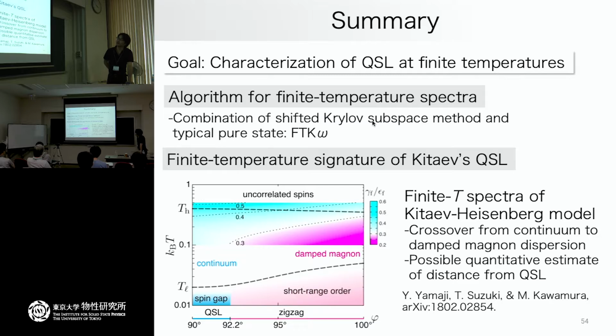And we found that the finite temperature signature of the Kitaev spin liquid phase really appears in the peak width of the spin excitation spectrum. This ratio gives us a crossover behavior from the continuum excitation spectra to the damped magnon spectrum. And maybe it gives us a possible way to characterize how distant your materials are from the Kitaev spin liquid limit.